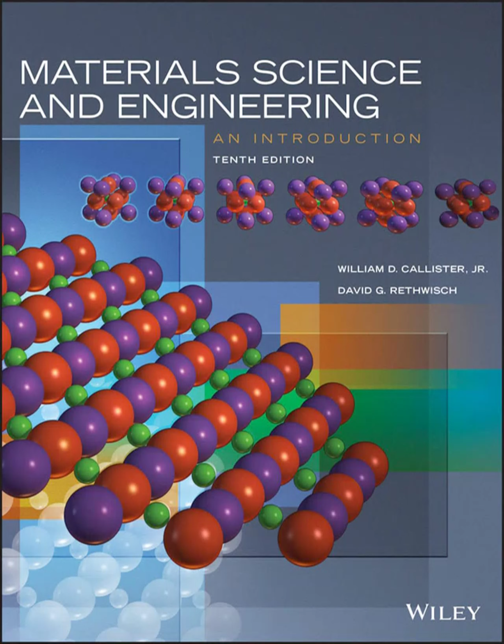Now, if you look at a plot of log D versus 1/T for various metals diffusing in silicon: copper, gold, silver, and aluminum, at 500 degrees C, the difference is staggering. The diffusion coefficient for aluminum in silicon is incredibly small, about 3.6 by 10 to the minus 26. That's vanishingly small. It is, and it's at least 8 orders of magnitude. That's 100 million times lower than the diffusion coefficients for copper, gold, or silver in silicon at the same temperature.